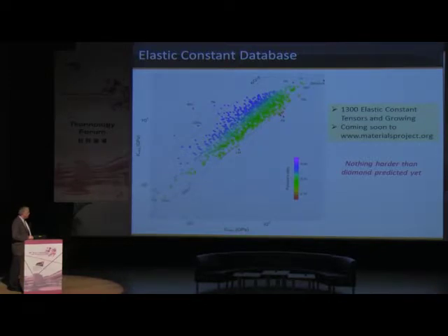So what's plotted here is the calculated shear modulus and the calculated bulk modulus on these two different axes. And this ratio K over G, again, is a measure of ductility. So K over G of 1 would be low ductility, K over G of 5 would be very high ductility. And all these materials that we've looked at so far lie somewhere in between, with a few exceptions. These are also colored by Poisson ratio. So as you go towards more ductile, you're seeing that the Poisson ratio is getting bigger. Basically, we now have 1,300 materials that we know the elastic tensors for, and within about 6 more months or a year, this number will probably double or triple, probably triple or quadruple actually.